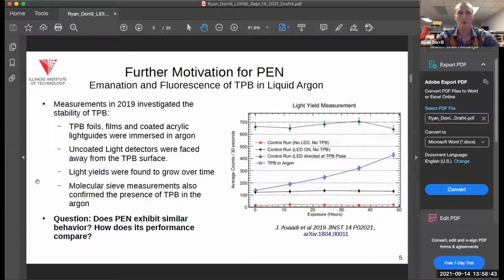So, further motivations: there's a study done in 2019, also by Jonathan Asadi, investigating the stability of TPB over time. Essentially what they did was immerse some light guides into liquid argon over a long period of about 72 hours. Some of these light guides were coated with TPB, others were not, and sometimes they also used foils. They observed count rates in their light detection system. With the things that weren't coated in TPB, the count rates were essentially stable, like you'd expect. But with the TPB, they saw counts that were rising over time. They followed this up with measurements by molecular sieve, and were able to see that the TPB had emanated into the liquid argon and hadn't been super stable.